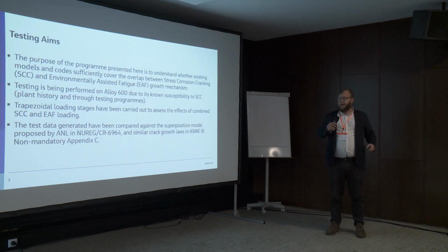I'm going to talk to you today about a testing program we've been carrying out to generate crack growth rates for alloy 600. The testing was designed to investigate the effects of both environmental fatigue and SCC on each other. So to do that, the main way we've been able to investigate the interplay is to carry out trapezoidal loading stages. So we will have a fatigue loading stage, but include a hold time in that.